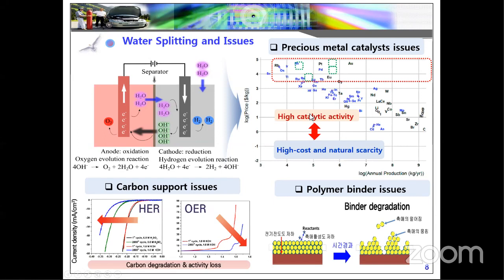You can see, when we fabricate these catalysts into electrode materials, we need some polymer binders. When we use polymer binders as well as conductive agents, during the stability test, especially the durability test, they degrade easily. The polymer easily degrades because, in KOH media or sulfuric acid media, basic or acidic media, it easily dissolves, and carbon corrosion happens easily. Then these binders may reduce the stability. You can see the HER: in the first cycle, the potential is very low, and as you increase the number of cycles, the potential moves towards higher and higher potentials.